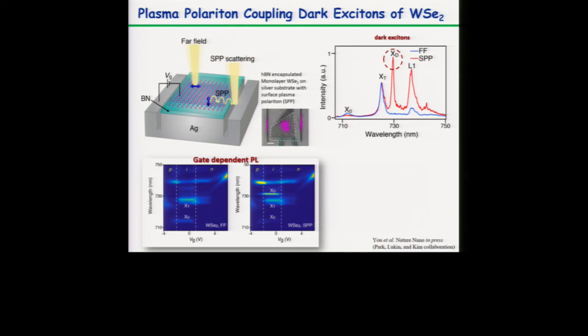In gate dependence, you also can, I mean, this is silver, so you can use silver to gate as well. You can gate the sample, and you can compare the gate-dependent PL map on the far-field collection, or also on the surface plasmon polariton, I mean, outside, on the grating, and you can see that the dark exciton is bright in this region when we're collecting from the SPPs. So this can also be useful for plasmonic optical modulators or switches, since we can use this silver to either excite this dark exciton or not, with the gate on the bottom.